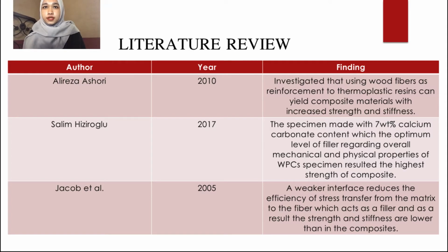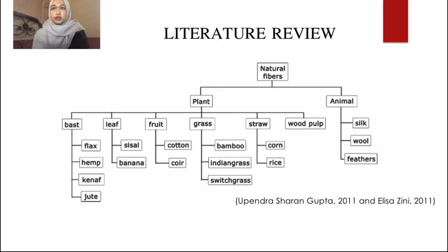This is from Salim Hiziroglu. The specimen was made with 7% calcium carbonate content, which is the optimal level of filler regarding overall mechanical and physical properties of rubber wood flour plastic composite, and the specimen resulted in the highest strength of composite. The advantages of the use of natural fiber in composite are their renewability, biodegradability, non-toxicity, good insulation properties, and low machine wear.